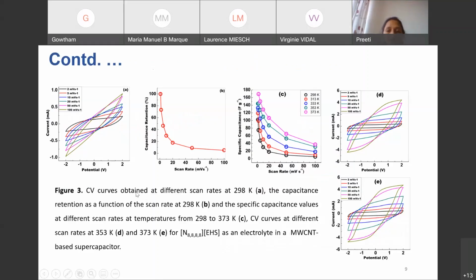Now, what was the interesting thing which we observed here is that when we obtained the CV curves, we saw that at lower scan rate, we got the rectangular shape of CVs at room temperature, like 298 Kelvin. But as we increase the scan rate, the CV distorts, going beyond the rectangular shape. And this might be because of the high viscosity of the ionic liquid at low temperature or at room temperature,